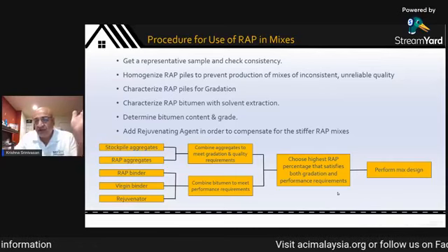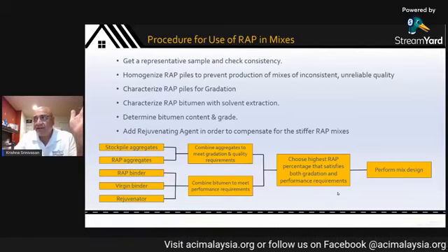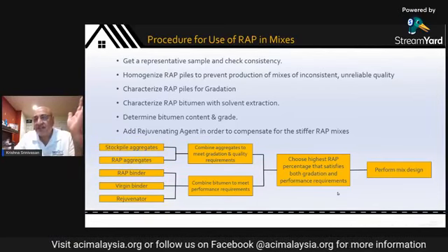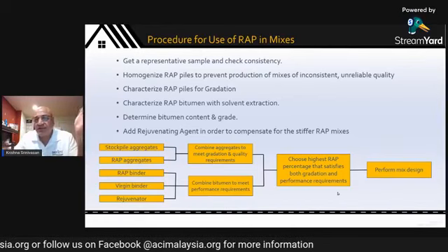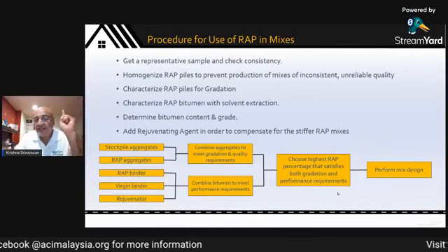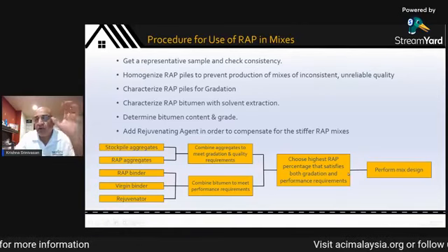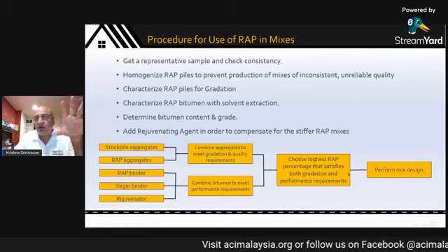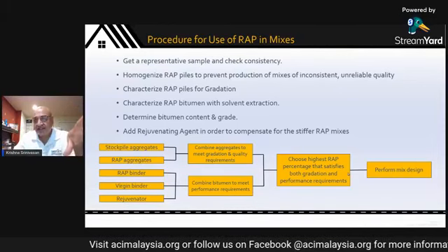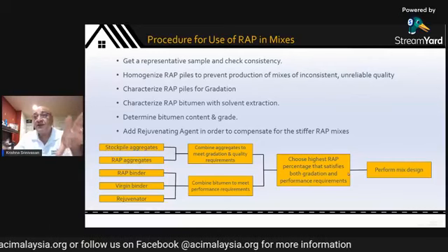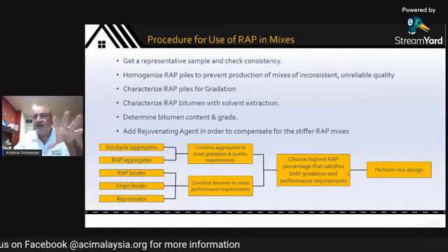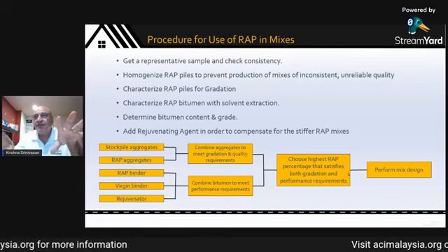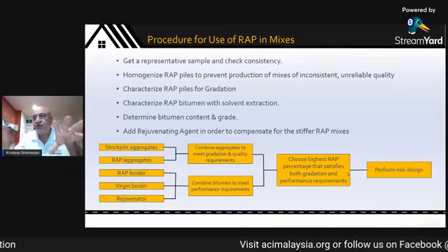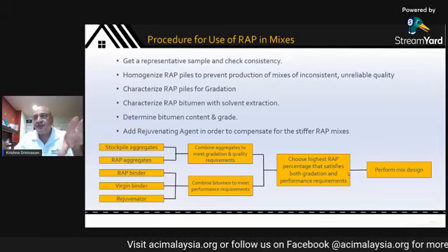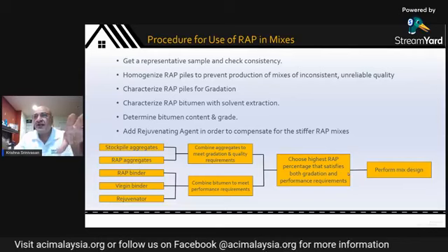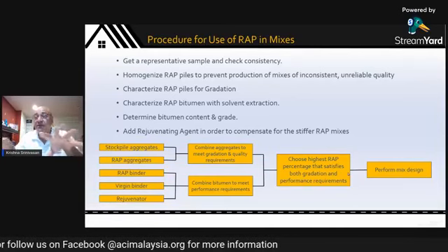Remember when I told you earlier on that you should break down your RAP into coarse, medium, and fine. That is accepted. Some people just break it down into coarse and fine. Some people just work with one grade. In general, as a rule of thumb, the more the separation into different particle sizes of your RAP, the higher the RAP content you can put in your mix. That's one of the underlying principles, which is why, not simply from a material consistency point of view, you want to separate your RAP into different piles based on sizes. You also do that so that you're able to incorporate more and more RAP into your mix.